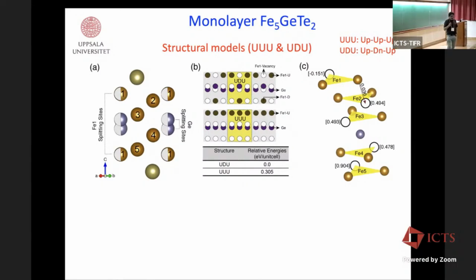What does it mean? First of all, in experimental STM, people have seen a √3 by √3 superstructure rotated by 30 degrees. That basically means in the unit cell, there are 3 iron atoms in each atomic plane, √3 by √3. So that's why in UUU and UDU, 3 such letters appear, meaning that when all 3 iron atoms are in the upper plane, we can call it UUU. They can also be in the down plane, we can call them DDD, it doesn't matter, they're equivalent. Or there can be another scenario where there's a split occupation. Some of them are in the upper layer, some of them in the down layer.